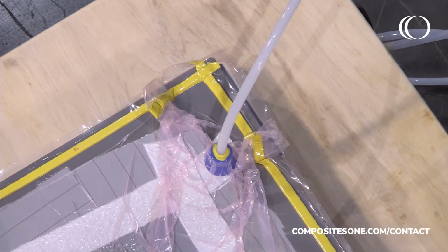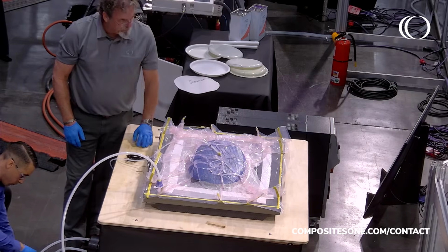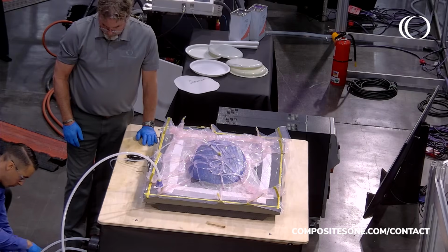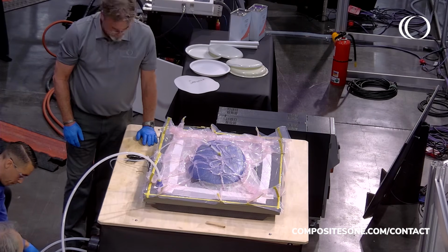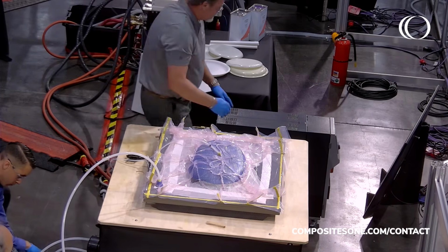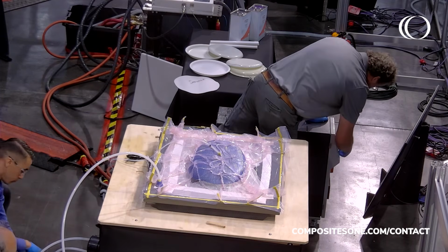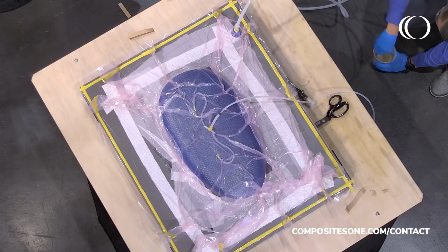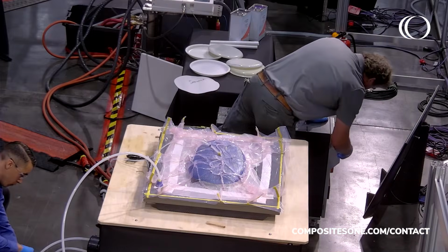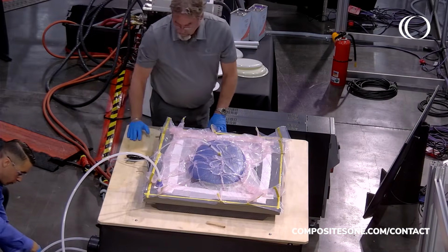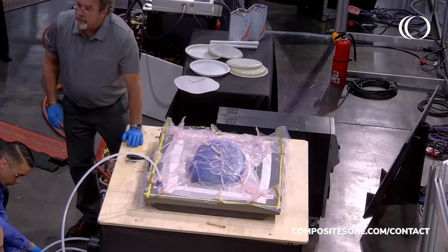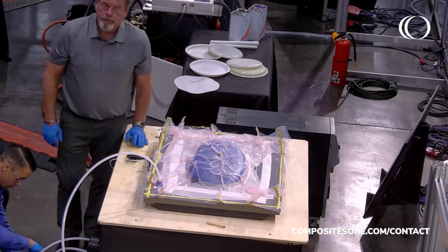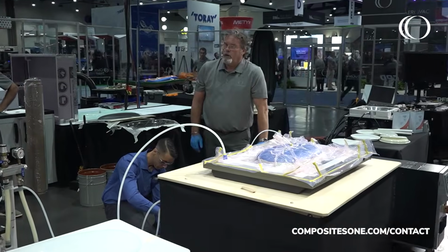So we're going to go ahead and mix the resin. They've done the final leak check and approved the bag. And so we'll mix up the resin, and once that's fully mixed, we can open it up and introduce the resin in the part. That's one of the great things about the vacuum infusion process: we have a virtually unlimited setup time, so we can make sure all the fibers and process materials are placed correctly and not have to worry about the open time of the resin until everything is fully approved.